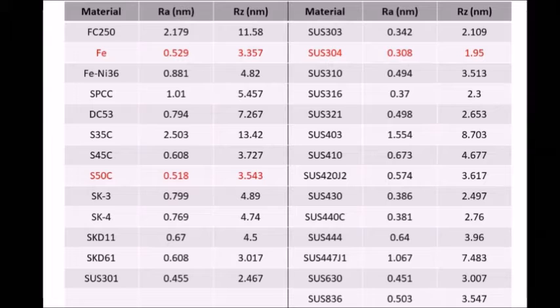The list on the right are stainless steel materials. We have polished 15 types of stainless steels. The best Ra is 0.3 nanometers, and Rz about 1.95 nanometers from the material stainless steel 304.